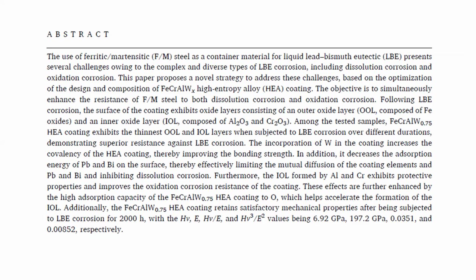Following LBE corrosion, the surface of the coating exhibits an oxide layer consisting of an outer oxide layer (OOL) composed of iron oxides and an inner oxide layer (IOL) composed of aluminum oxide and chromium trioxide. Among the test samples, the FeCrAlW0.75 HEA coating exhibits the thinnest OOL and IOL when subjected to LBE corrosion over different durations.